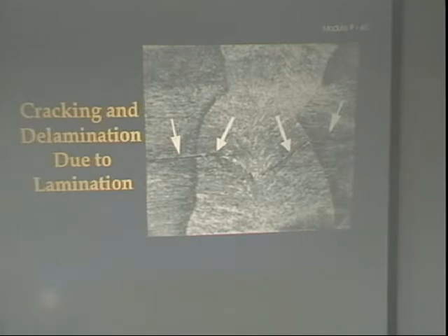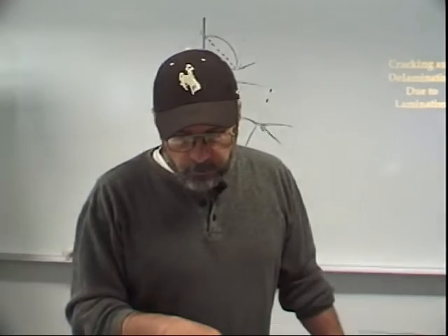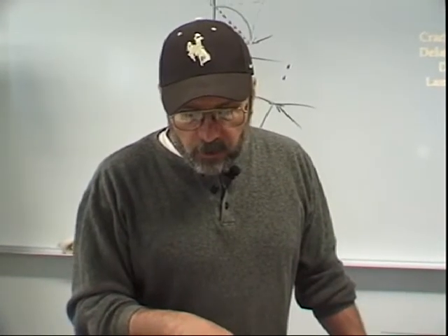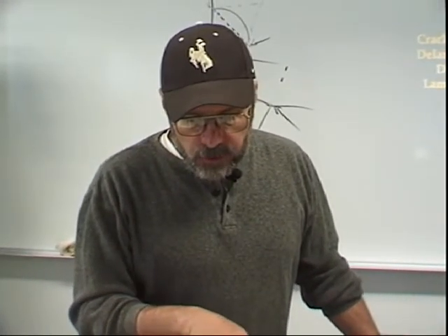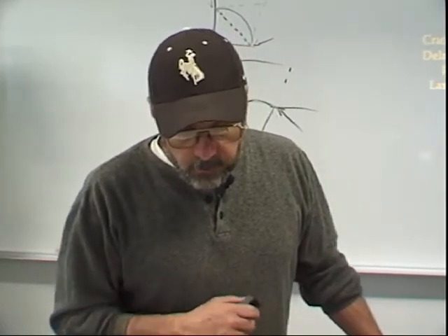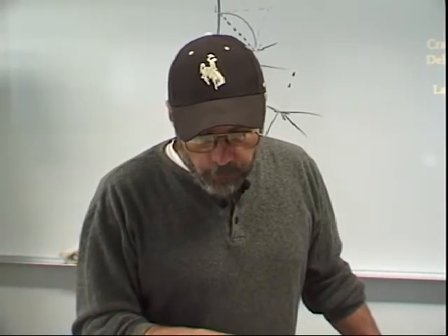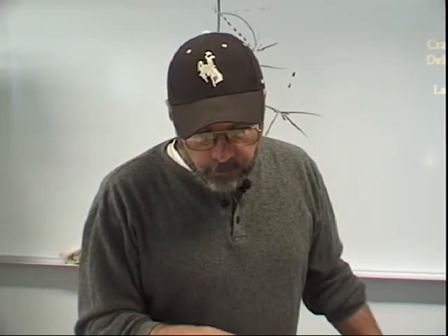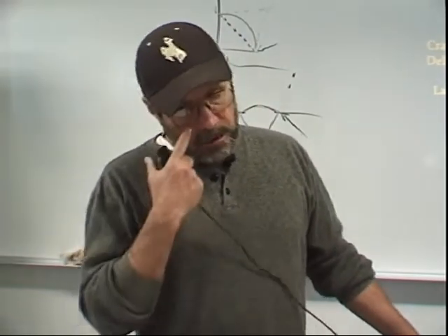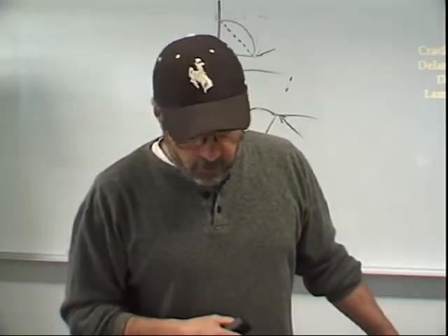So highlight that. Then drop down to the third paragraph and highlight that, where it says, if a lamination is present on the surface of a weld preparation, it can cause further problems during welding. In such a case, weld metal cracks can propagate from the lamination due to a concentration of stress. And an example of this is what we're seeing in 9.44. Another problem related to the presence of laminations open to the groove face is that they are prime sites for the accumulation of hydrogen. We talked about hydrogen before, how they can form molecules and cause additional cracking.